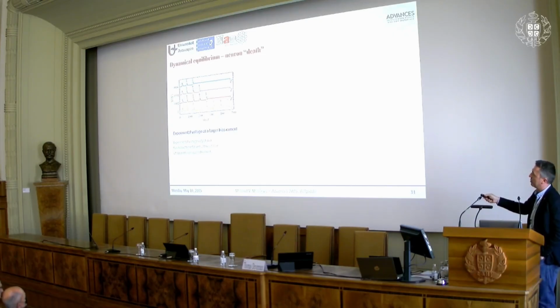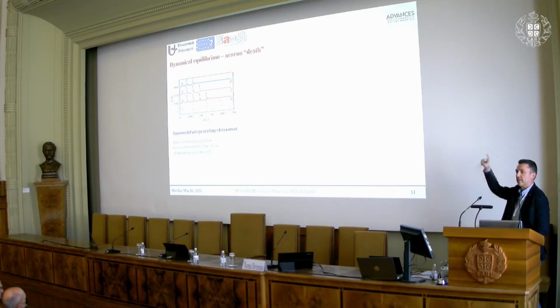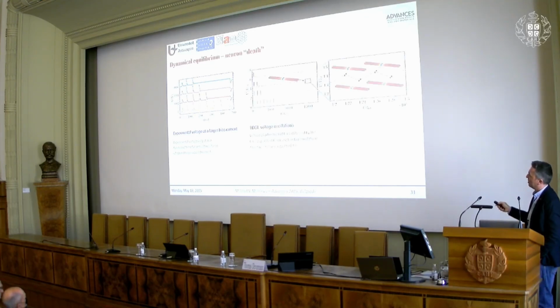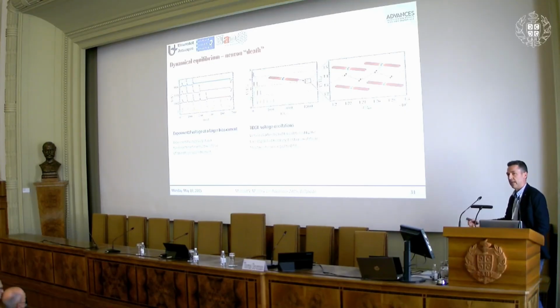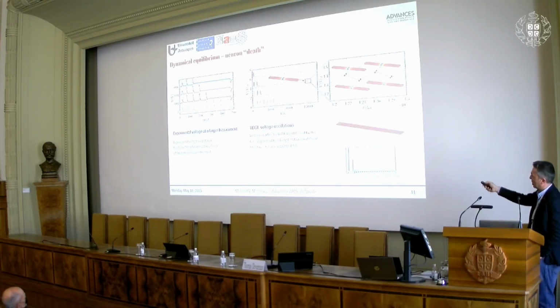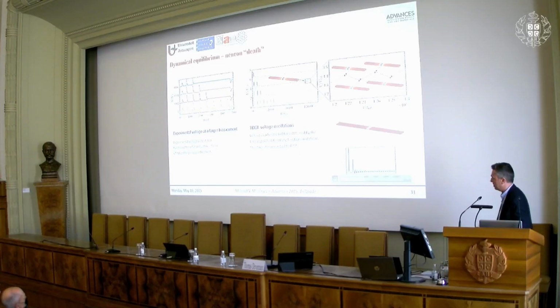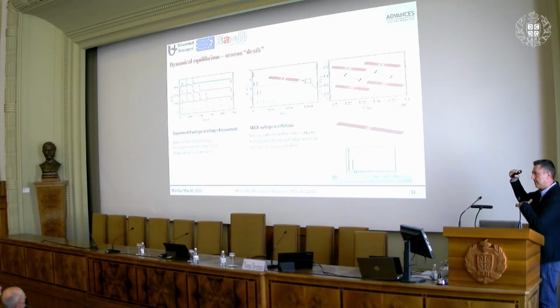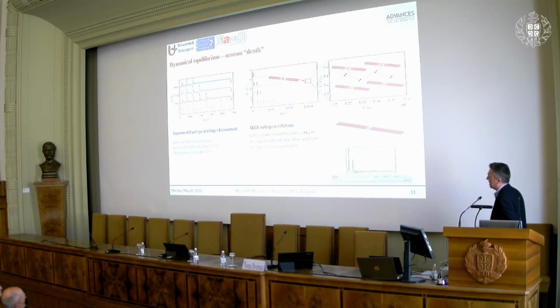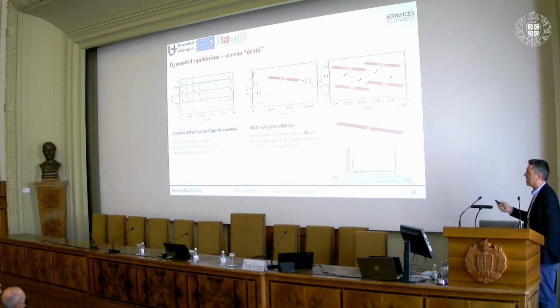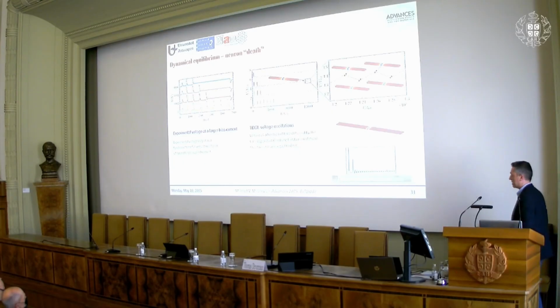What happens is that instead of bouncing from the hotspot to the superconducting state, hotspot to the superconducting state, the system prefers to go into the phase slip state and remains permanently in the phase slip state. So this is what it looks like in simulations, the voltage versus time. It goes up and down, hotspot, hotspot, and then finally just remains in this phase slip state all the time. And that's not what we want for the neuron. So we have to stay within a range of currents where we can fully control this spike behavior. This range of currents and the frequencies of spikes will depend on the shunt resistor as well as the properties of the superconducting stripe.